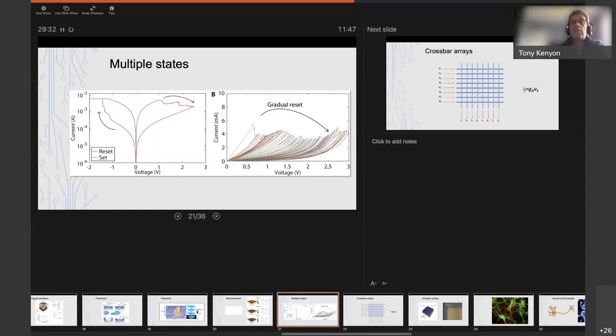So if you took a slice, say, through say 1 volt here, you can see there are multiple resistance states. So we're going through one cycle and then reducing the voltage here, and then we're gradually increasing the voltage, and we go through that cycle and we increase the voltage a little bit more, and we have that cycle, and so on and so on and so on. And just by gradually increasing this voltage that we apply before we reduce it again, we can access many, many different resistance states. So that allows us then to think about these devices not just as memories that have two states, but